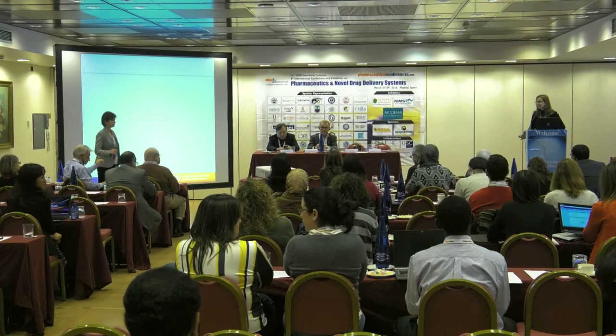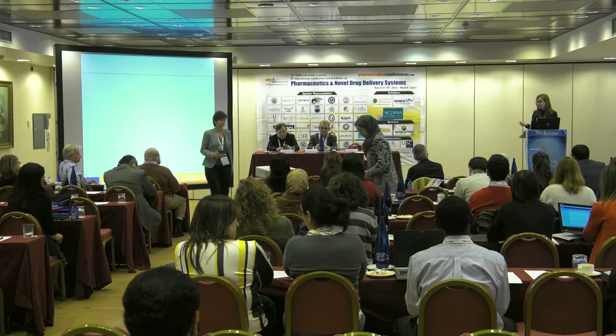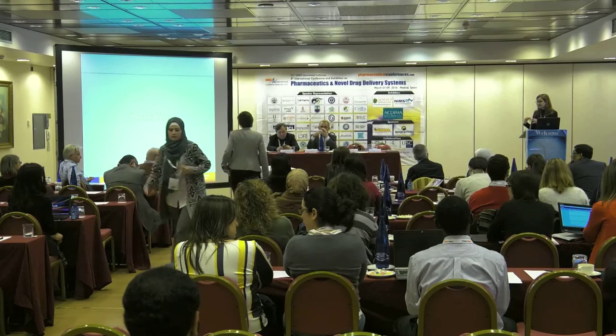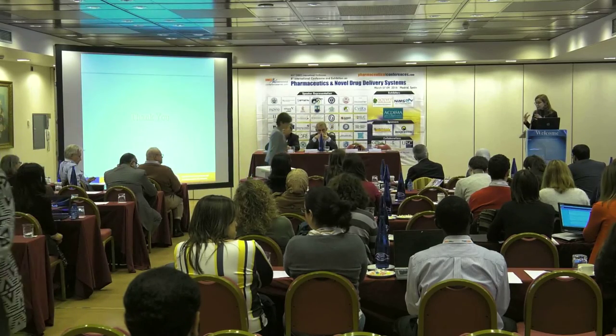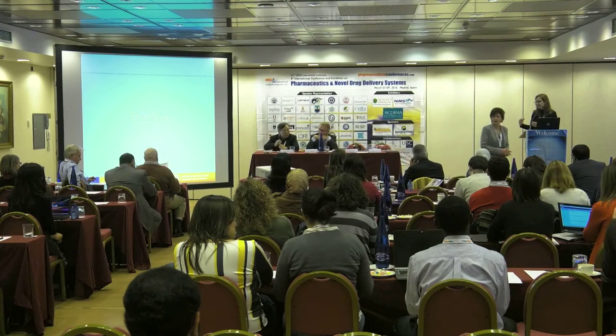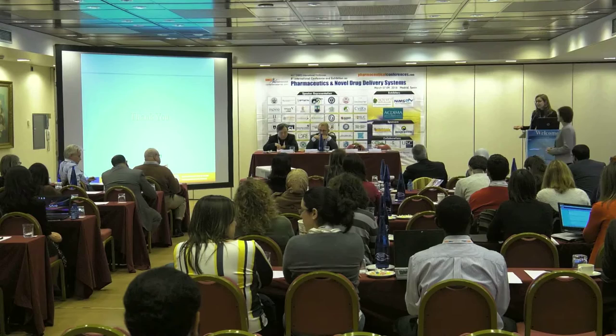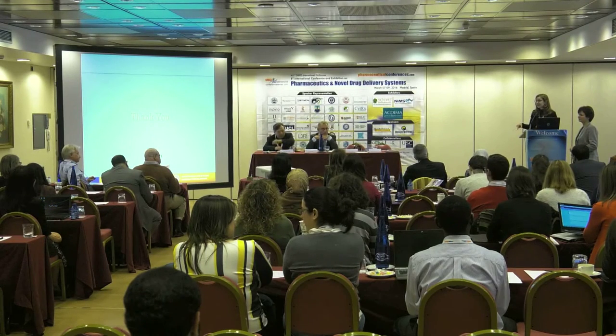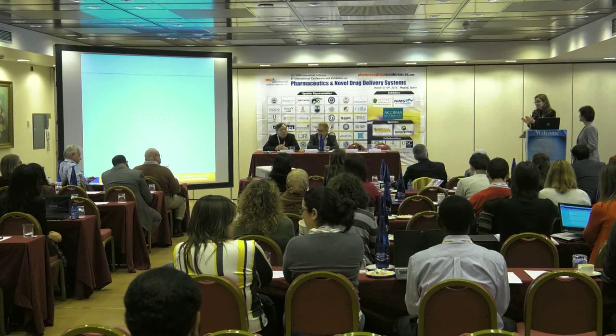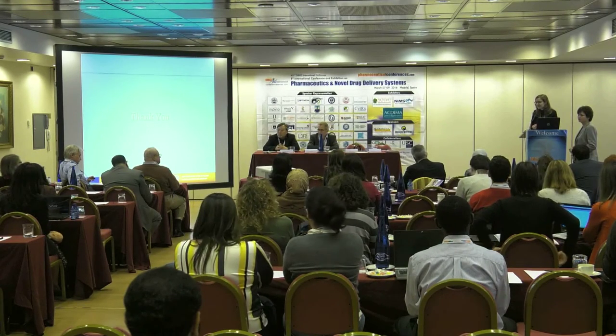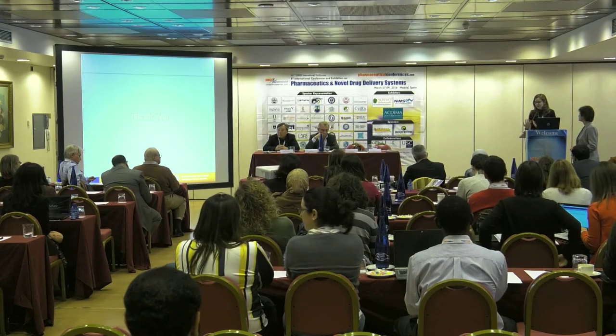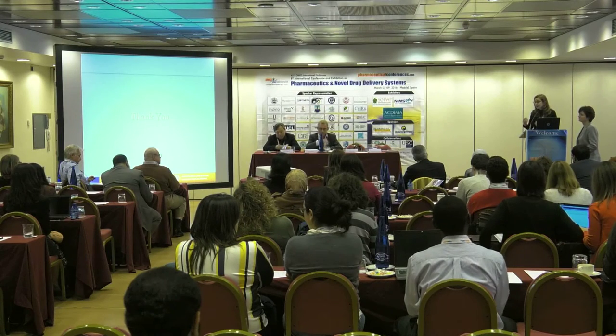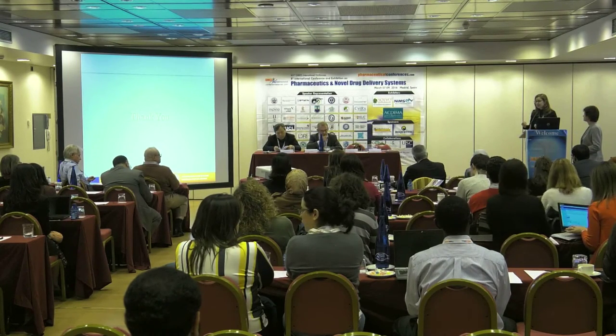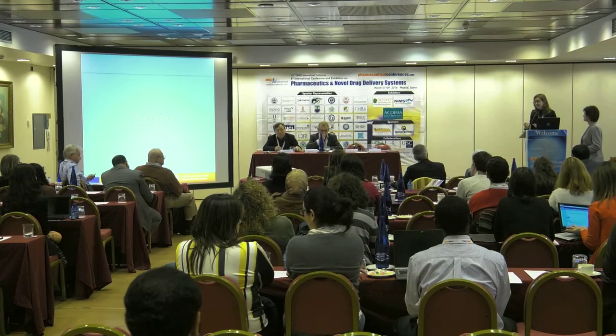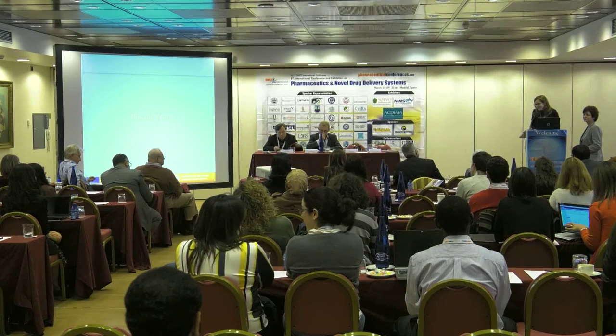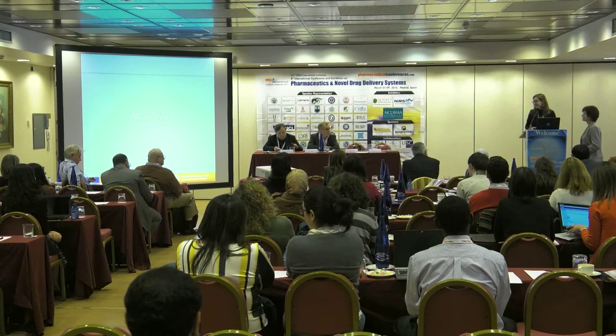We have obtained pulsatile release from capsules made up of hydrophilic swellable polymers. We have also investigated the possibility of coating these delivery systems prepared by hot processing by spray coating. For example, we have applied an enteric coating on HPC capsules. The possibility of preparing multi-layered capsules only by the use of hot processing techniques is something very complicated from an engineering point of view, because it requires a co-extrusion process or something like that. Probably by three-dimensional printing, it may be easier. We would be very interested, but we have not yet attempted. We are in an earlier stage of attempts.